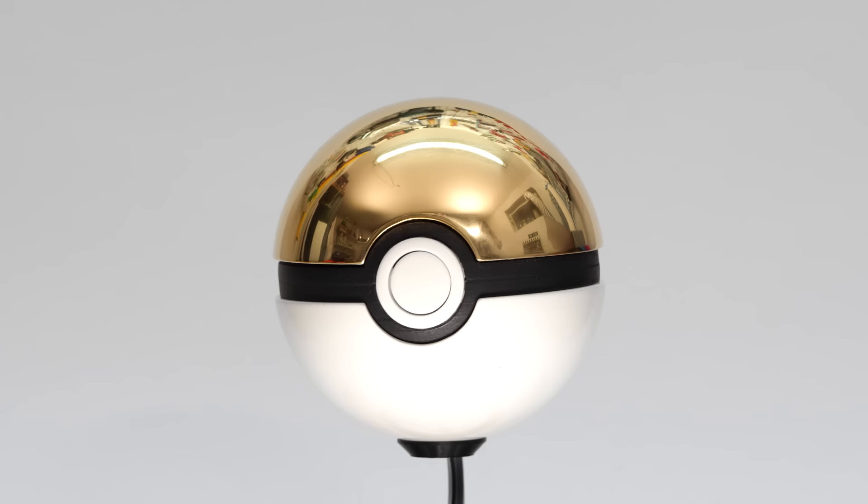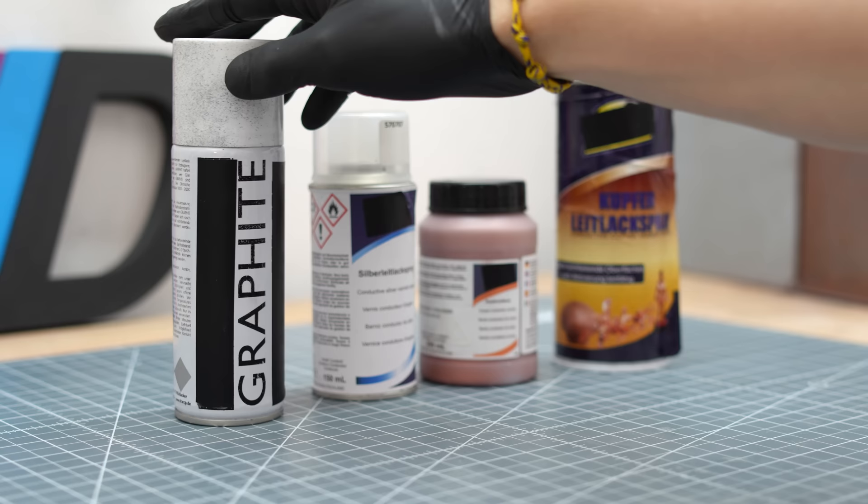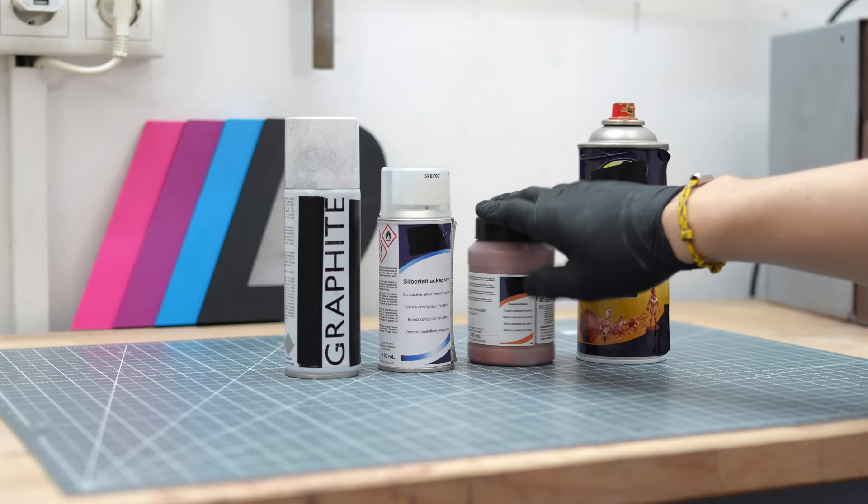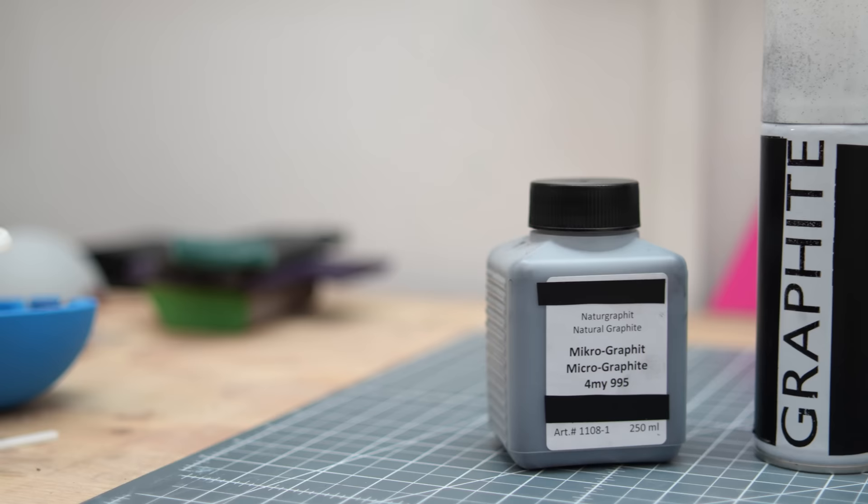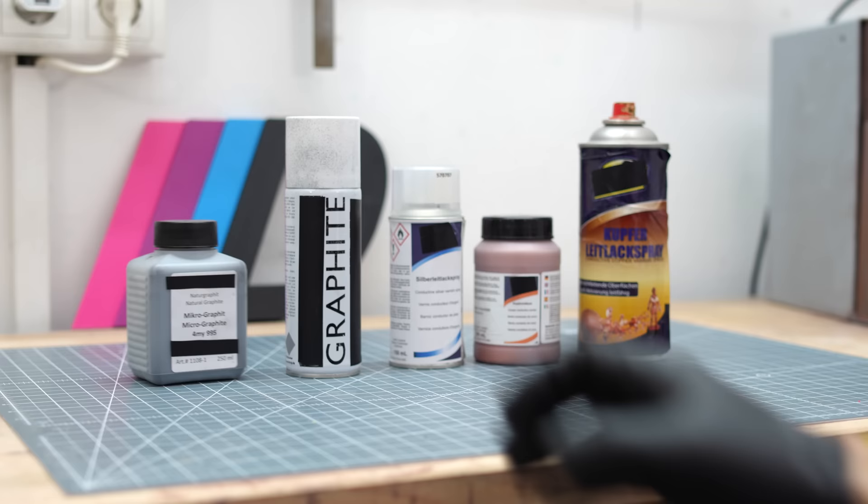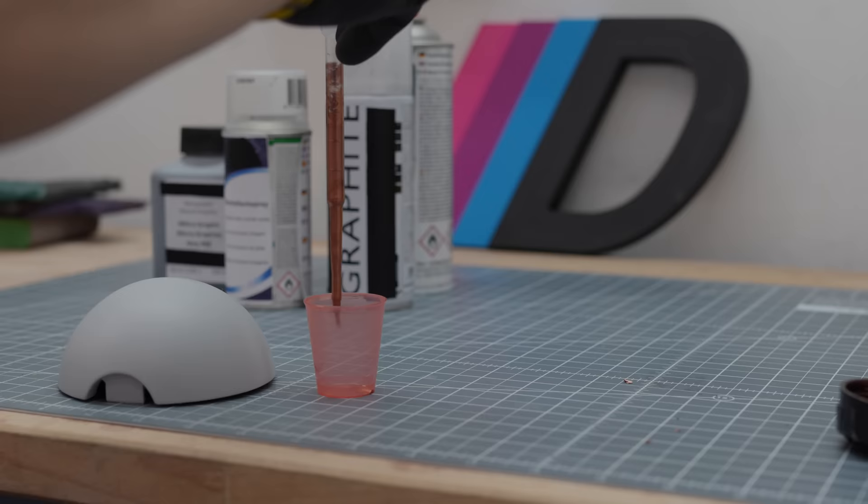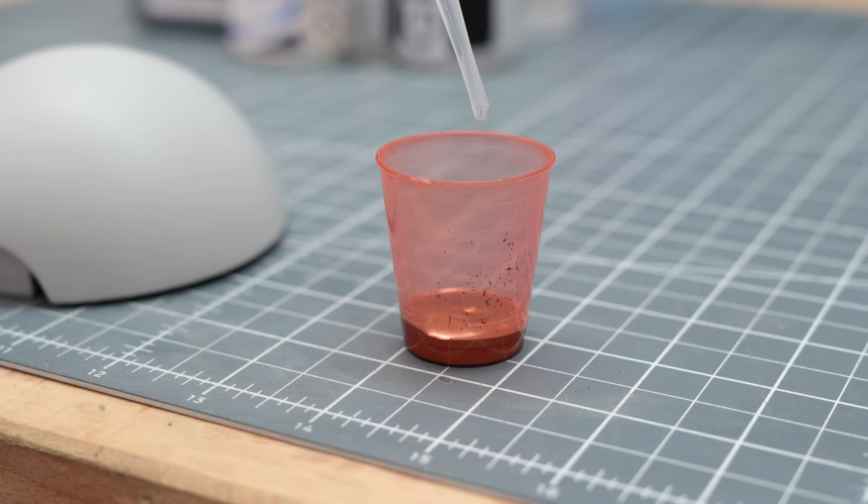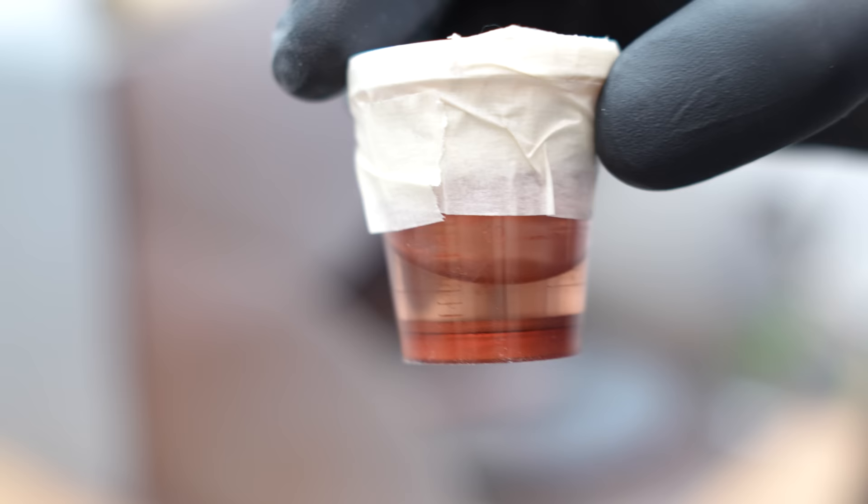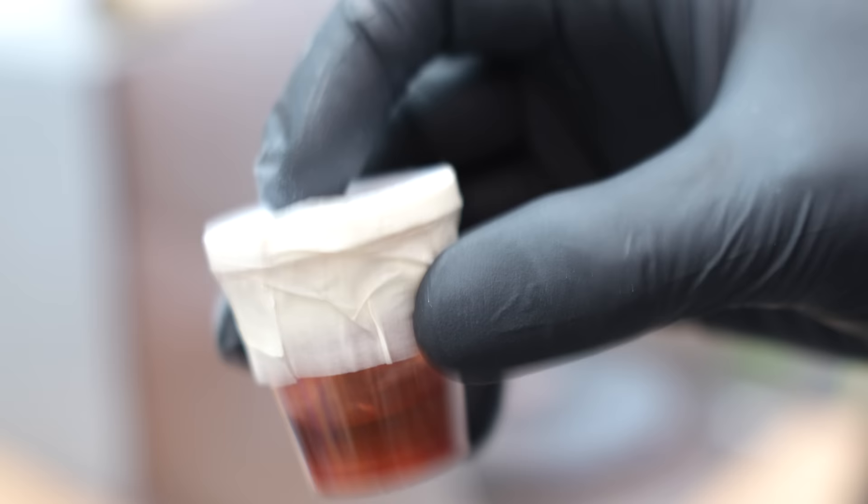The top shell will be gold plated, therefore we need to electroform it first. Regardless of what you use, it all works well as long as you know what you're doing. There are copper conductive paints, silver conductive paints, and the possibility of graphite paints. I actually experimented with micro graphite and we'll see when I present the results. For this project I am using copper conductive paint again. I dilute it with acetone in a 1 to 2 ratio. For those wondering why, it's an electrically conductive paint on which we can deposit metal with electricity. The goal is to achieve a thick layer of copper.